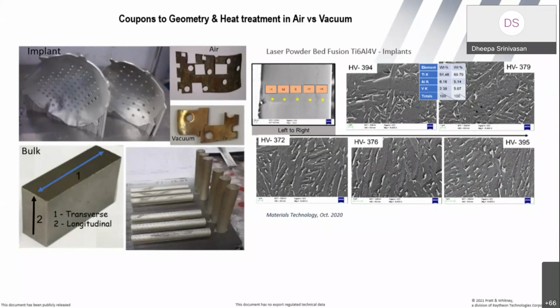Should we do water quenching? Should we do air cooling? Should we do furnace cooling? Should we do direct aging? Should we do a simple stress relieving? All these are very, very preliminary, very, very important questions to ask before carrying out the respective heat treatments. Okay, because it can completely change the microstructure from the left to right, especially in titanium alloys which are prone to oxygen affinity. And if microstructure is affected, it will definitely affect the mechanical properties, provided the application is one that requires the bulk and the actual part to be the same, right?